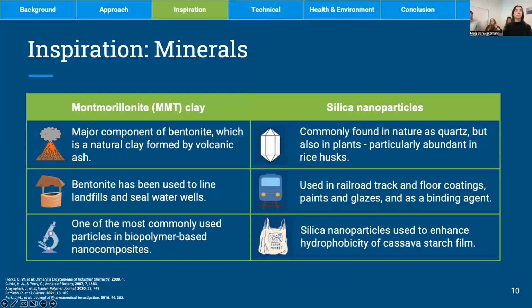Bentonite has many different usages. It's been used to line landfills and seal water wells because of its ability to reduce water vapor transmission rate, and this contains montmorillonite clay. And MMT, which is the abbreviation that we'll use, is one of the most commonly used particles in biopolymer-based nanocomposites. And we saw that in the literature that we found.